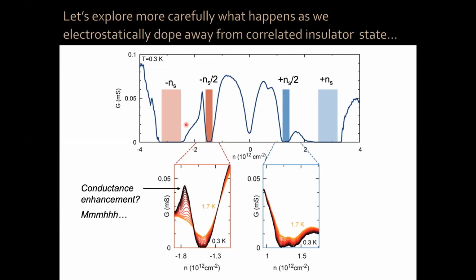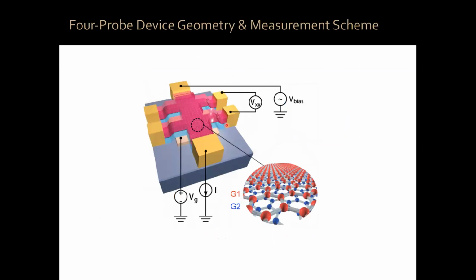Now the thing is, this data had been taken in a geometry where we had only 2 terminals, source and drain, attached to the graphene. And that is because if you're looking for an insulator state, which is what we were looking at the time, you can do 2-terminal geometry measurements. This introduces a small series resistance with your device, but if you're going to measure infinite resistance, adding some small resistance, who cares? However, if you want to see if something conducts very well, you don't want to have that series resistance in series, okay? So what we did is we made devices in a 4-terminal geometry.